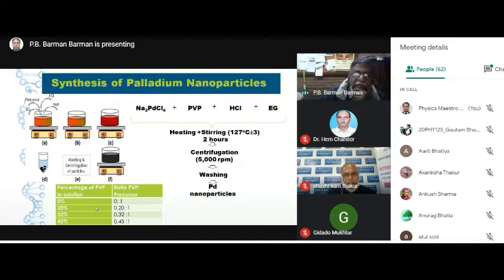And we have used this method: simply heating and stirring at 127 degrees plus minus 3 degrees for 2 hours. This is practically whatever parameters we have chosen, the optimal parameters. And after washing, we get the palladium nanoparticles.